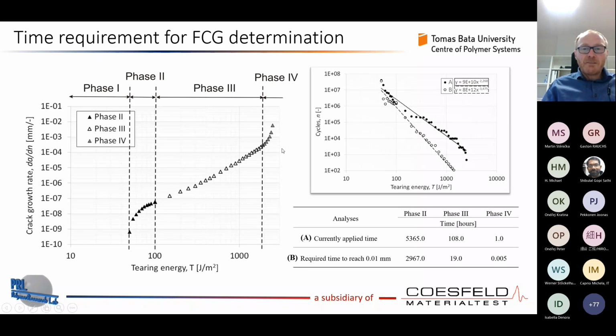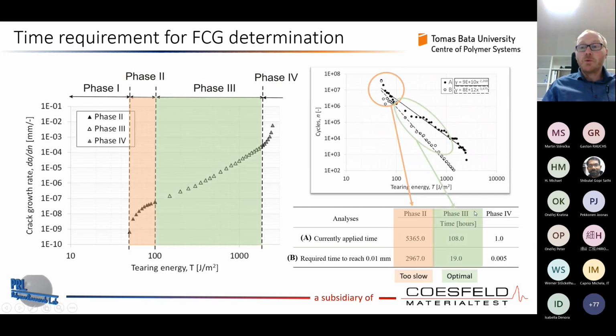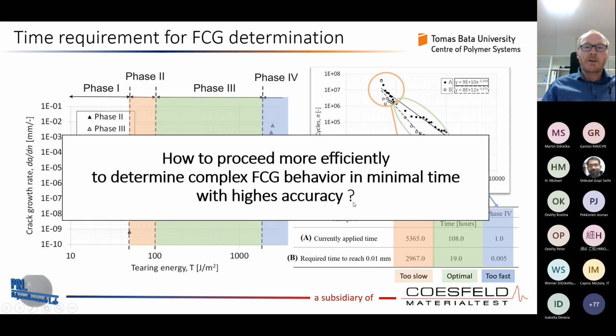So that's very important information, because this is really too slow. You need a lot of time to make such an investigation. This is, yeah, okay, optimal. We can do it very quickly. And this is too fast. We need a very, very accurate system to get such data in a very precise way. So these two, phase 2 and phase 4, would need some improvement to get them accurately. And in phase 3, we know that we need to measure as it is, however, we need to more precisely define the specific function compared to the power law.